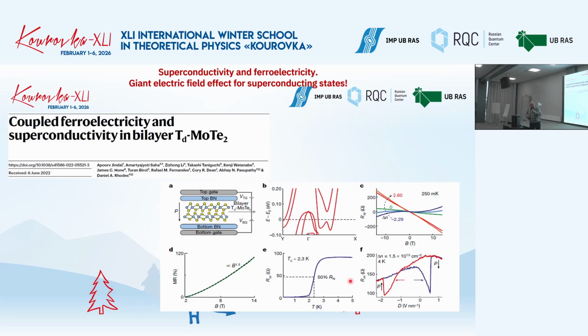What is much more important, look to the right, this bottom picture, you can see that by controlling this D large, which is basically some difference between the gate potentials, you can first change the dipole moment, and simultaneously you can control the resistance. And you see that by changing this applied electric potential, you just have these drops of resistance, switching of resistance from zero to non-zero. And it's a sort of hysteretic behavior. I will discuss it more. It's just for a start, for the beginning. So let me just continue.